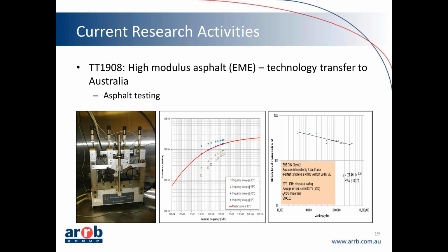So why are we doing all this, I can potentially hear some people asking. The reason is that doing this further analysis of the fatigue relates a little bit more closely to what's happening in the field. And you can see there that the average air voids content of the beams using the saturated surface dry method is around about 3.1%. Standard, usually we would do 5 plus or minus 0.5.